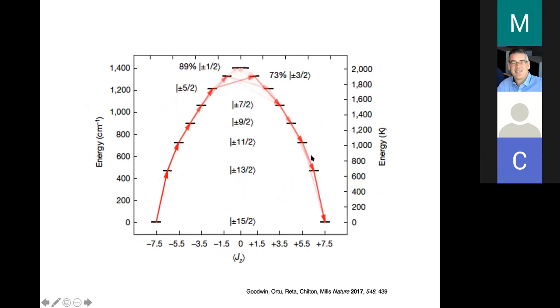Yeah, so you're referring to this, it would be inverted in this case. And what that means is that your lowest energy state is not polarized. So if plus or minus 1/2 is at the bottom and all the others are high, you can transition between plus or minus 1/2 and lose polarity without this activation barrier. And so it's critical to create a ligand field that has the splitting so that the higher moment M sub j's are lowest in energy.